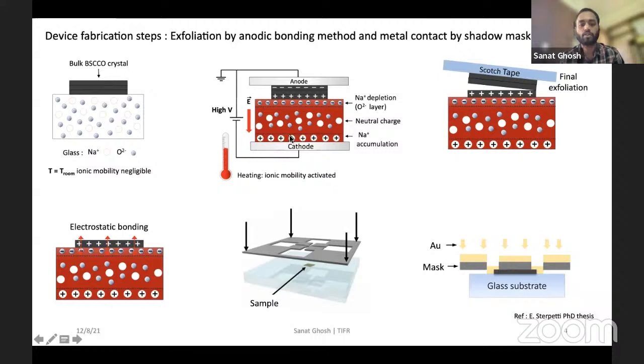When we heat it, the sodium ions get mobile in the glass substrate, and then those can move in the glass. After that we apply a very high voltage across the BSCCO and the glass. What happens is that because of this large electric field, the sodium ions move to one of the surfaces, and because of this an image charge forms at the BSCCO crystal, and that electrostatically bonds the first few layers of BSCCO. Then we peel off the bulk from the substrate with the usual Scotch tape, and we get thin layers of BSCCO. After that, we make contacts with the BSCCO flake by shadow mask evaporation. We don't do any chemical processing of the system, as it is known that this degrades the quality of the superconductor. So we align a mask with the flake and then deposit metal contacts.